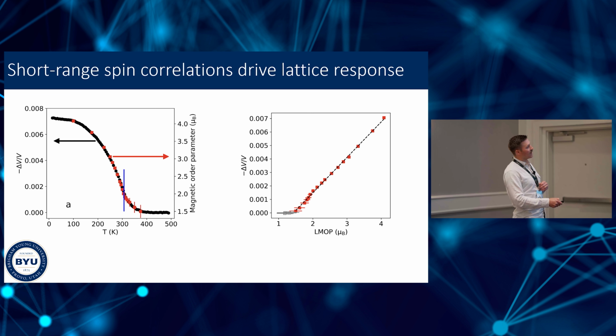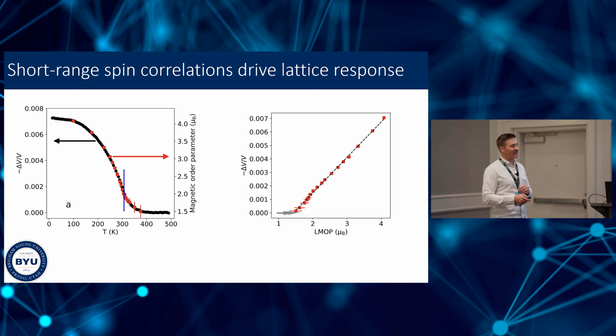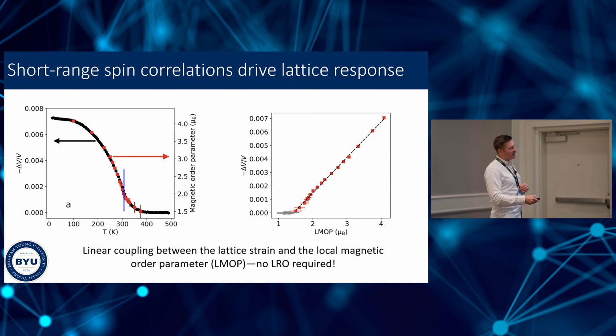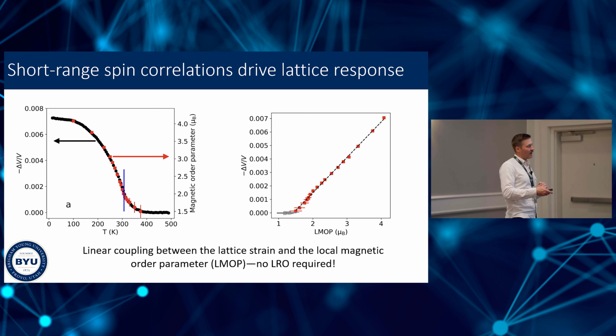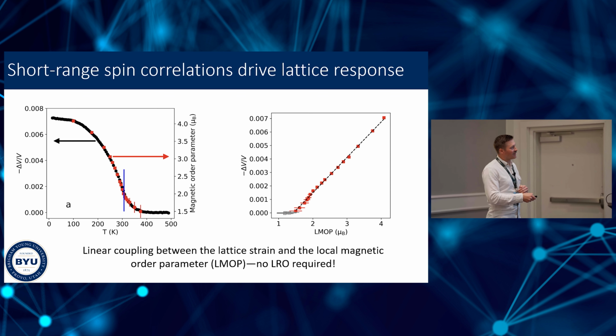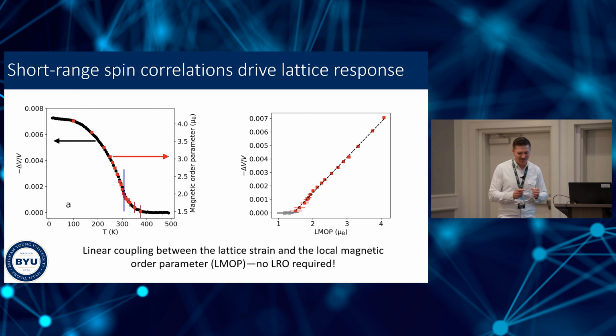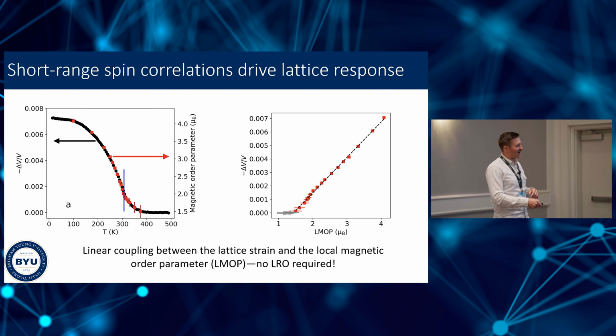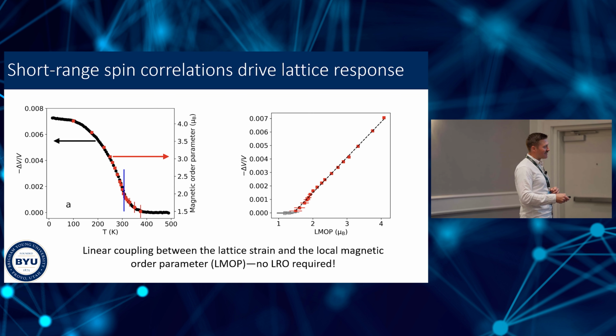And in fact, if you plot one versus the other, the fractional volume change versus the local magnetic order parameter, we have a very clear linear relationship, okay? I want to emphasize, these points down here represent magnetic PDF data collected in the paramagnetic state, where no long-range magnetic correlations exist. So this linear trend begins with short-range correlations in the paramagnetic state, already driving this long-range change in the unit cell volume of the material. So the linear coupling between the lattice strain and the magnetism occurs to the local magnetic order parameter. No long-range order is required. Okay, so forget about your average crystallographic structure. All we care about is the local short-range magnetic correlations in this case.